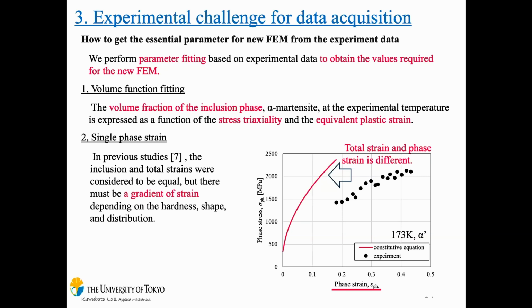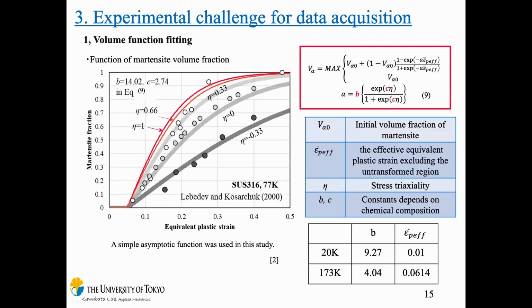Firstly, I explain the volume fraction fitting. We assume equation 9 to express it. This equation is based on Lebedev's previous research. The parameter B expresses the effect of temperature and chemical composition, and the parameter C expresses the effect of stress triaxiality. In this study, parameter C from the previous research is used, and parameter B is determined to fit the experiment result.